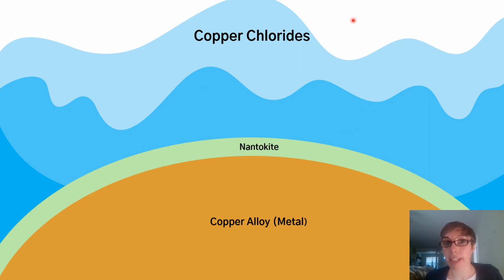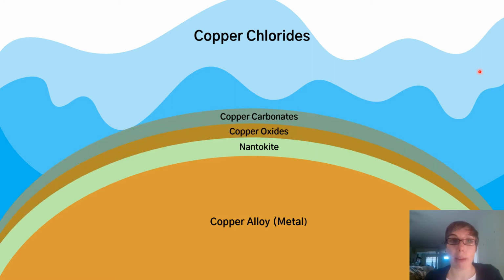As the nantokite is forming, so too are other copper corrosion products such as copper oxides and carbonates, which you are probably more familiar with, as they make up the majority of that sort of brown-green patina that you typically see on the surface of copper artifacts. The problem is that these corrosion products tend to form over the nantokite layer.